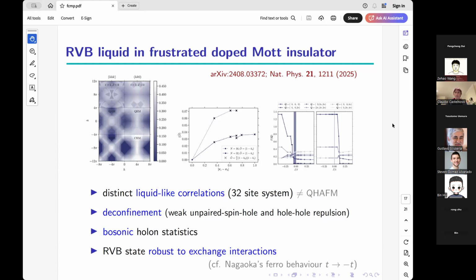And the last bit of information here is what happens if you add exchange interactions? You make U not infinite but finite, and then the spins can talk to one another directly through exchange. And you can ignore the right panel here, which is for the Nagaoka effect on the square lattice for comparison. For the counter Nagaoka effect, there is a window shaded in gray here of stability that gets larger if you go from 1 hole to 2 holes to 3 holes. So it's suggestive that this system is stable at weak enough interactions and finite density. But again, we're looking at small system sizes. I wouldn't make too strong of a claim at this point. Further work is needed, but it's pointing at least in the right direction, in the promising direction.